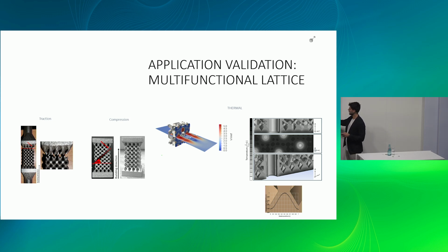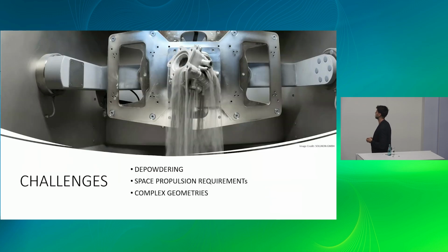So we still need a little bit of cone here for support in a much reduced way. But what can really be seen is that the temperature is concentrating in the center of the cone, which makes sense. You have a massive structure, so in a steady state, you have the most heat concentration in the middle, and due to the bad thermal conductivity of nickel-based alloys, there's kind of an inertia for the heat to actually escape, and that is what we try to minimize with this.